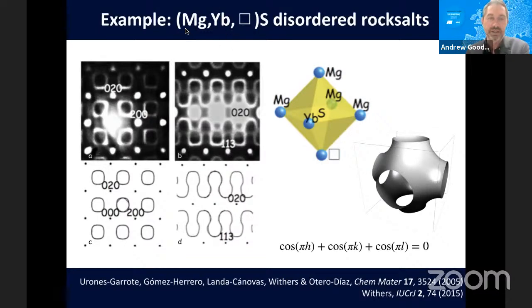This family, these disordered rock salts, which are actually closely related to what you might see in, say, some cathode materials. You have an ordered FCC sublattice of sulfur, and then a bunch of vacancies and different cations on the other sublattice. Here, magnesium, ytterbium, and vacancies. And if you make the chemically sensible assumption that around each sulfur, the mixture of species on the other sublattice reflects the overall composition, you can take that constraint and write it down in this mathematical expression here that traces a surface in reciprocal space that is related to where the diffuse scattering ends up. So here's an example of understanding the diffuse scattering in terms of something that has absolutely no parameters, just some chemical intuition.